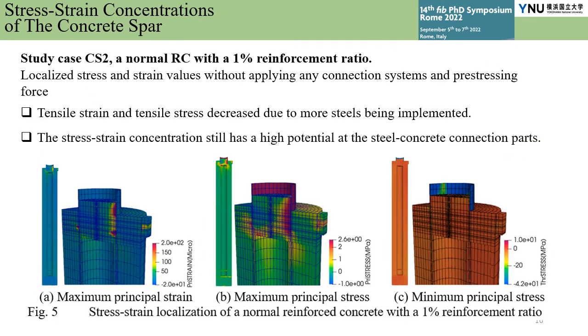Here is study case 2, a normal RC with 1% reinforcement ratio. The result shows a smaller red area compared to case 1 because more steel was implemented. However, the stress and strain concentration still has high potential at the steel-concrete connection part. Therefore, it is necessary to design the connection system at the critical location to lower the stress and strain.